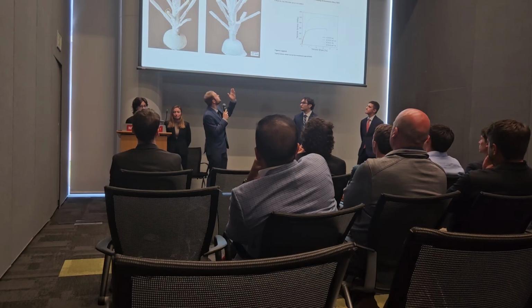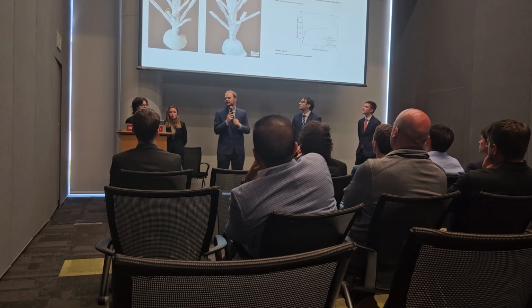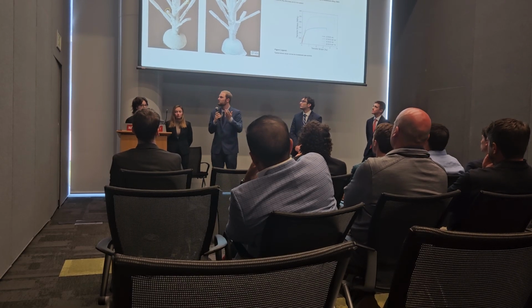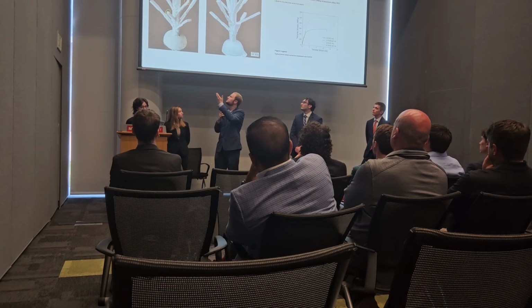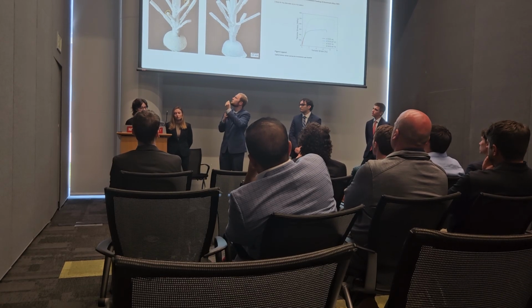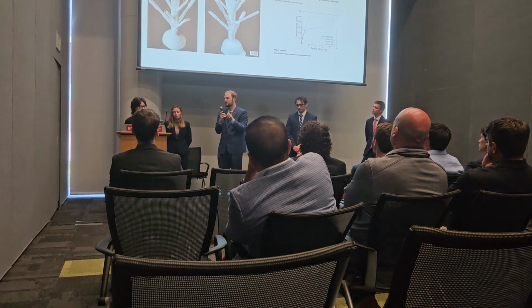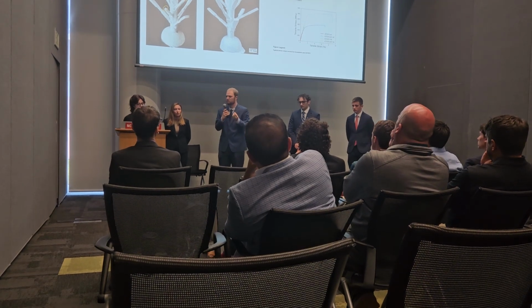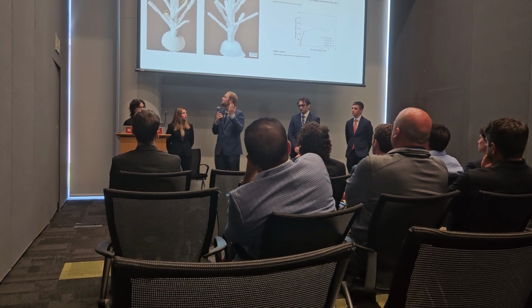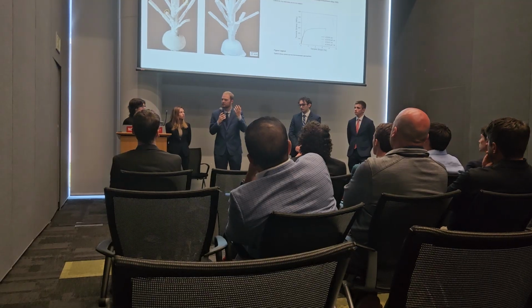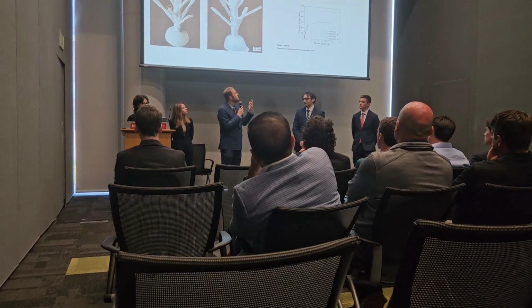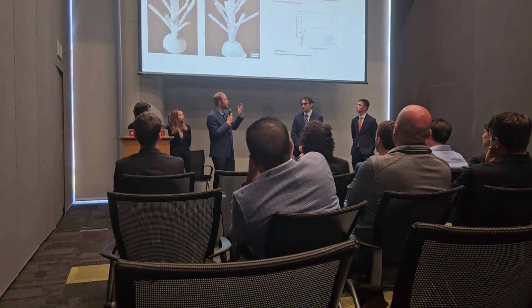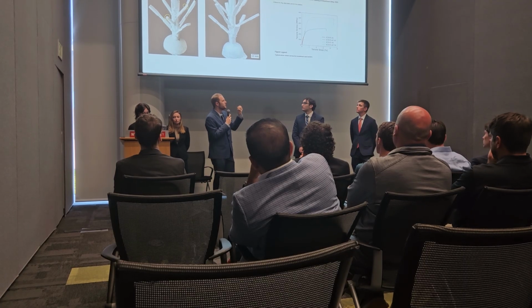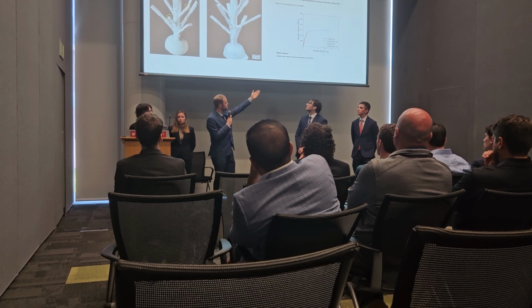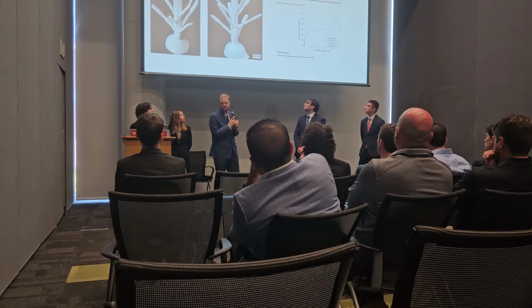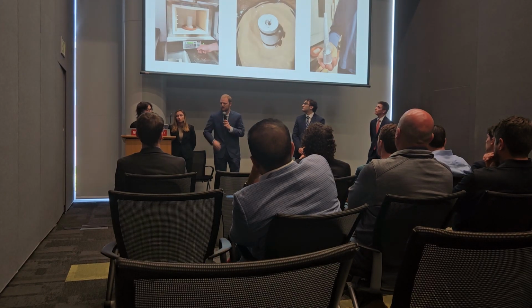So this is talking about that hot cracking. This is what the research paper found. They did this with dog bones, and as you can see, the normal 7075 casting has multiple hot cracks along pressure points and sensitive areas, which would lead to, for our design, cracking along the fins. When added with the titanium carbide nanocomposite, they had 10 out of 10 dog bones successful, and it led to an overall better flowability of the material and better tensile strength, as you can see from the chart.